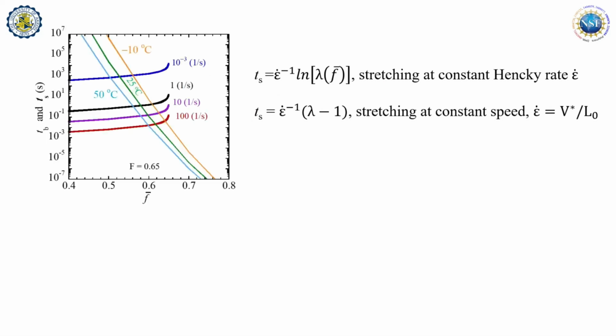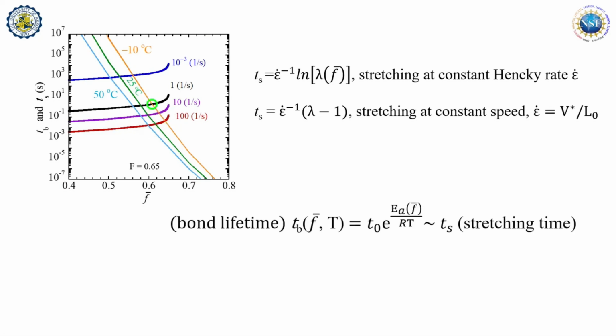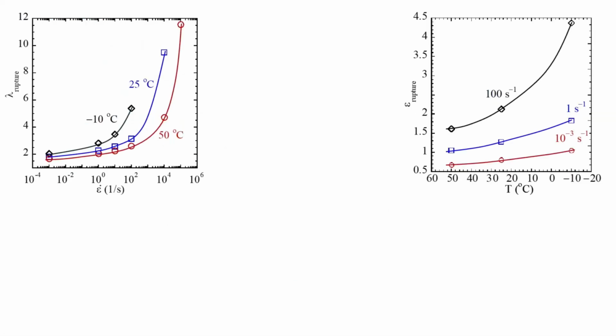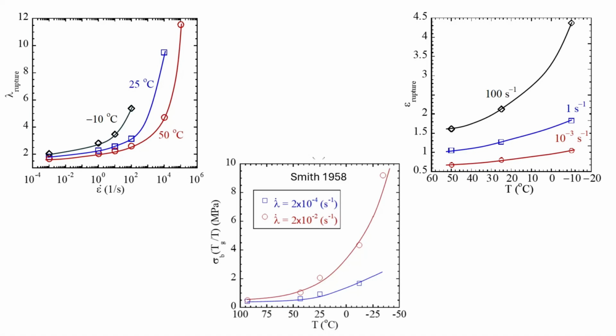So you can do a calculation. You can show the lifetime crashes down, and I start to take a little more time as I stretch more and more to build tension, and they meet at one point, which is when these 2 timescales are the same. You can get a numerical solution out of it based on a certain way to characterize the network structure. And here's what you find. At the lower rate, it changes little with temperature, and then it becomes a stronger dependence on temperature as you go to faster rates. Isn't that what I just showed you? That's Smith's data. So I have a theory. I mean, I tend to tease. I mean, for the first time, I can be quantitative.